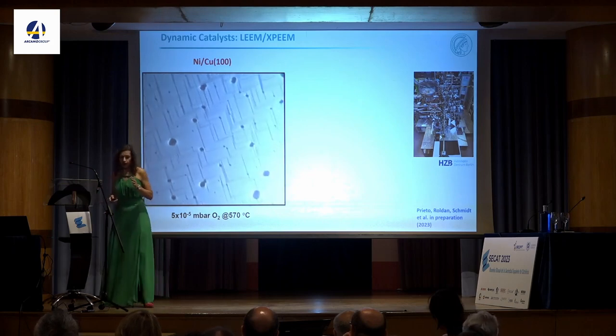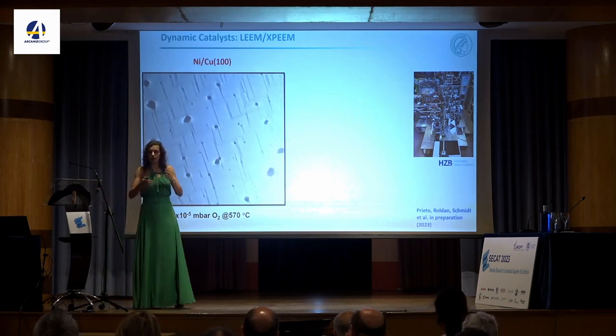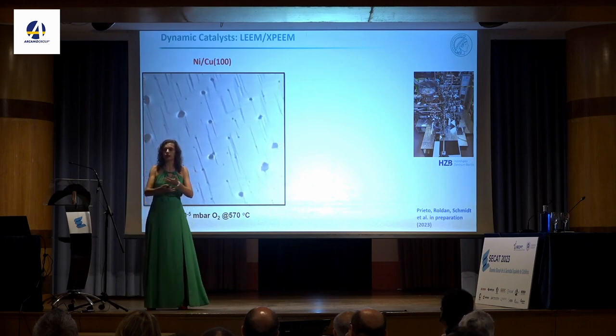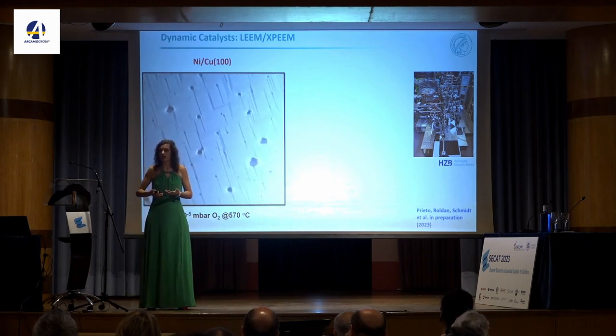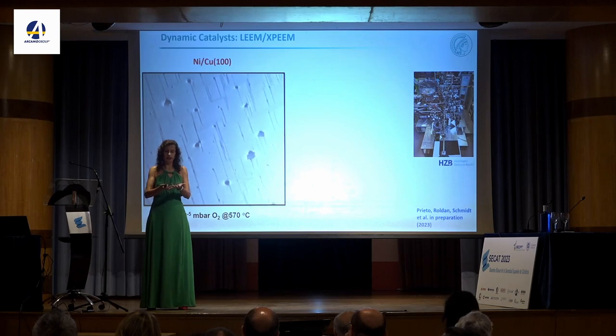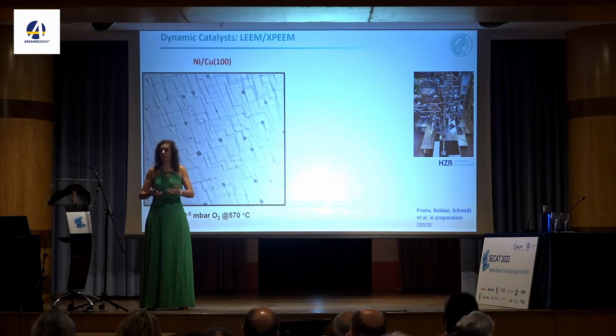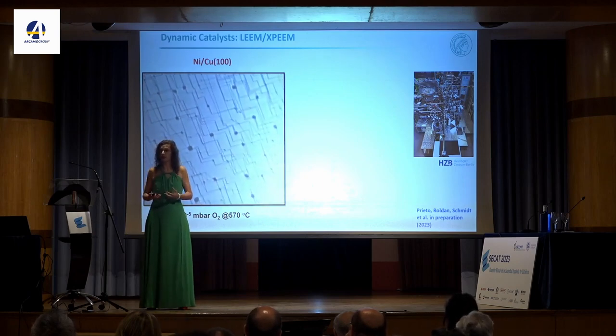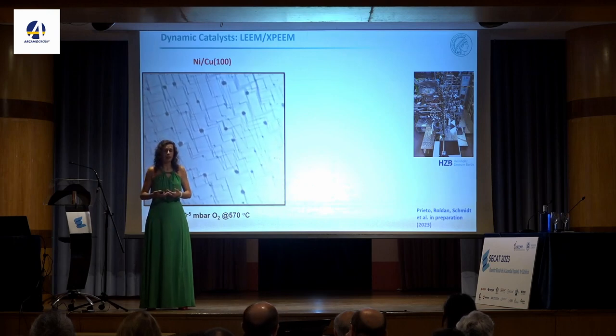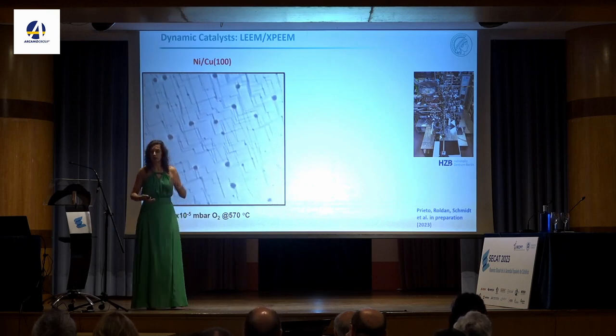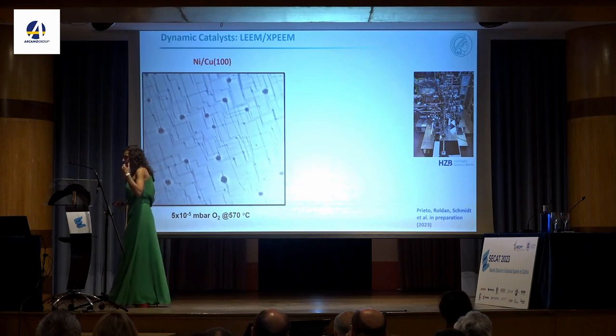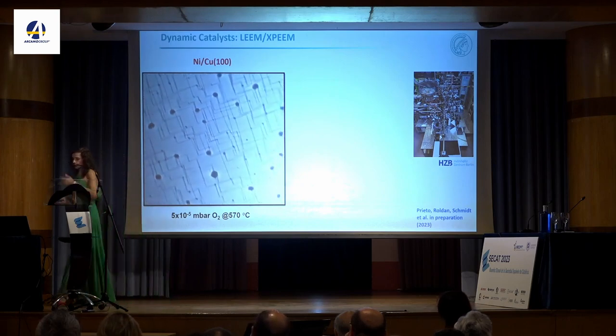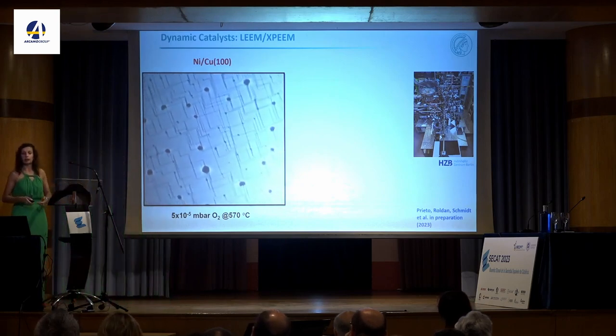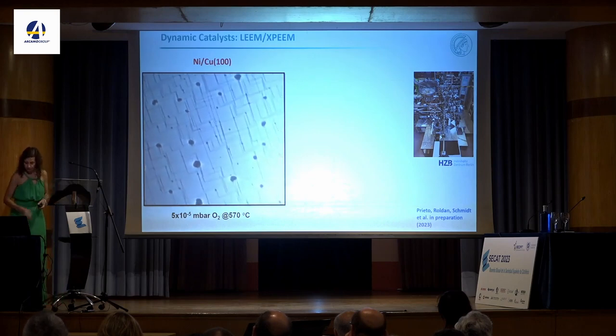So if you are working in theory, the transition that we need to make now is to forget about the static structures. So the structure that you are calculating is going to be changing, rearranging. There are going to be fluctuations. And these are going to be driven also by the environment. It could be a chemical potential. It could be a change in the temperature, change in gas pressure, and electrochemical conditions, the applied potential.